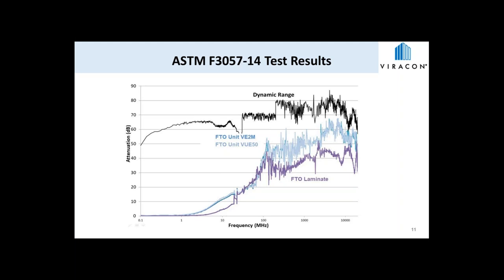Starting at about 100 megahertz, however, is the plane wave field, and this is where most of today's electronic devices operate. This is also where you can start to see the effect of the Low-E coating on the number 2 surface, as the FTO units have a higher attenuation than the FTO laminate within this range. Overall, though, the attenuation of each of the FTO units is approximately equal and very similar to what we saw in the IEEE test.